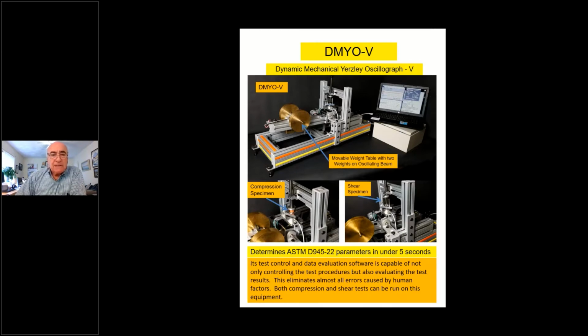As we change the moment of inertia of this equipment in dynamic testing, by the way, I should probably mention that the dynamic testing in compression mode and or shear mode are the two characteristic testing modes. The dynamic testing, and then we also do a hysteresis testing, and finally creep testing and the compression set test. So all these can be done on this equipment within short period of time. Dynamic testing can be between 3 and 5 seconds. Within 5 seconds, it depends on how elastic and how plastic the sample is.